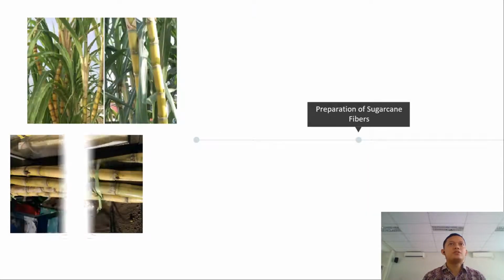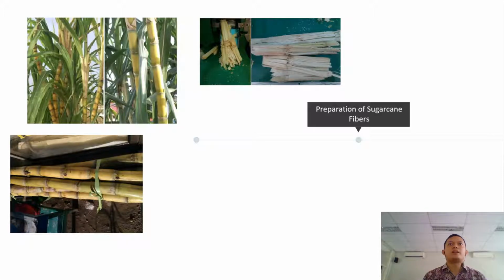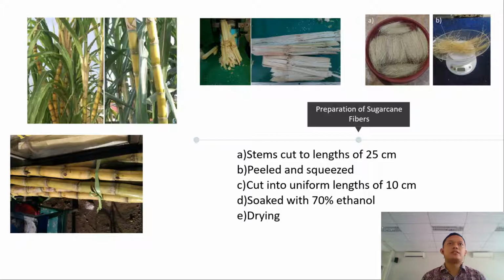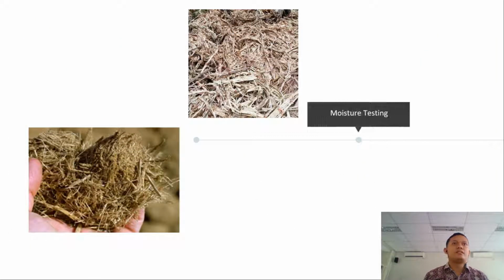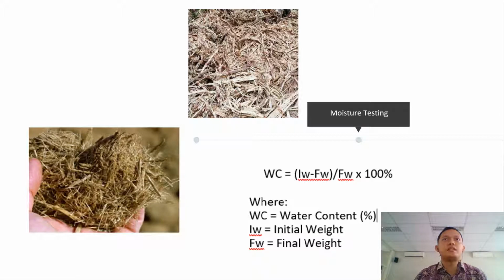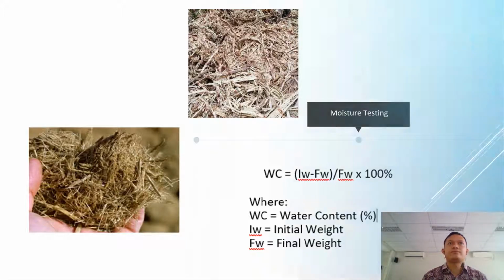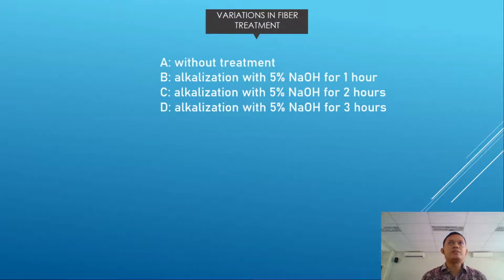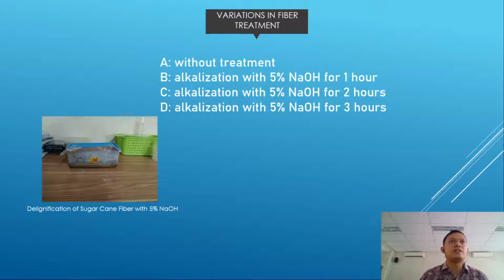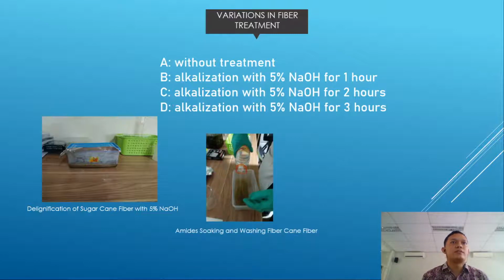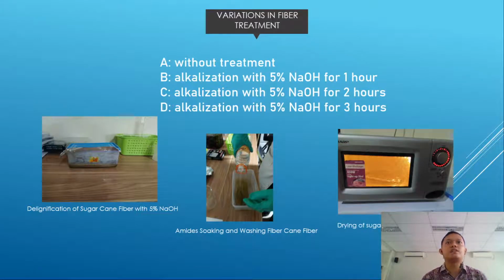In the methods, we prepared the sugarcane fibers in Balikpapan. We cut and then squeezed using a press to make pulp. There are also other preparations: cutting into uniform lengths of 10 centimeters, soaking with ethanol to make it clean, drying, and then weighing. The first test is moisture testing, so we need to make sure how much moisture is in the sugarcane. In the variation of fiber treatment, we have four: without treatment, and alkalization for 1 hour, 2 hours, and 3 hours. Then we treat in the box like in this picture, and then dry in the oven.